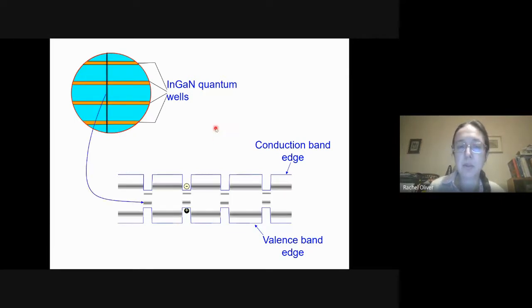What happens when we introduce a defect running through the material, one of these threading dislocations, these lines of mistake in the crystal that we saw in the transmission electron microscopy image? Well, the band gap of a material is very much a consequence of its periodicity. The defect breaks the periodicity, and therefore it essentially affects the band gap. It introduces states in the band gap, and those states are present both in the gallium nitride barriers and in the quantum wells, because the dislocation runs through both of them. And that means there are new routes for the electron and hole to recombine, which mean that heat is given out rather than light. That makes our device inefficient.